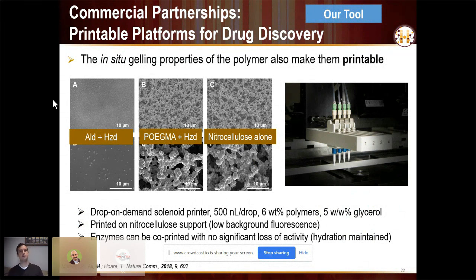so the amount of these materials that are required to do a comprehensive screen. So what we did is we actually did drop-on-demand solenoid printing, where we sequentially print the hydrazide polymer and the aldehyde polymer, usually the aldehyde first, simply because the nitrocellulose platform or any paper platform, there's always a few aldehyde groups around. So if you dry the aldehyde polymer, you can get a little bit of cross-linking to help to anchor that polymer, and as a result, the hydrogel formed by the hydrazone click chemistry to that surface.